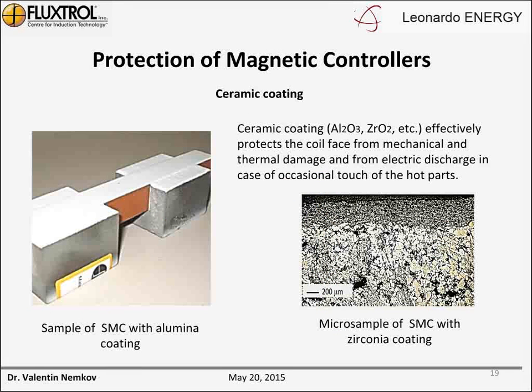Now, many induction coils are working in special environments, and we need to protect them from the environment or to protect the environment from them, such as in clean rooms. Ceramic coating may be effectively applied to the coil face, including the copper and the controller, and it can protect the coil from mechanical and thermal damage and from electric discharge in the case of occasional touch of the hot parts. Ceramic coating can be applied by thermal process, with a flame or plasma torch, or could be applied by brushing.